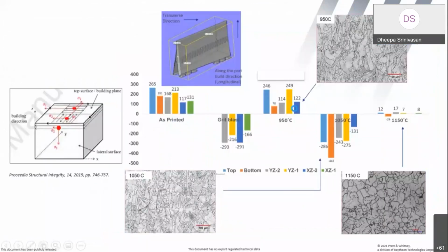So we took the coupon, did the sine square psi method, and then you can see the actual part here, on the surface and through thickness. The as-printed condition shows a tensile stress of almost 250 megapascal. Then when we went through the complete heat treatment, a cycle that I showed you finally, with the recrystallized microstructure, we were able to see the sinusoidal behavior of the residual stresses. And finally, at 1150 degrees centigrade, there is little or no stress. It is almost neutral. You can see it from the last slide. That is why we chose this particular condition. Though I showed it in the beginning, chronology wise, this is how we chose it.